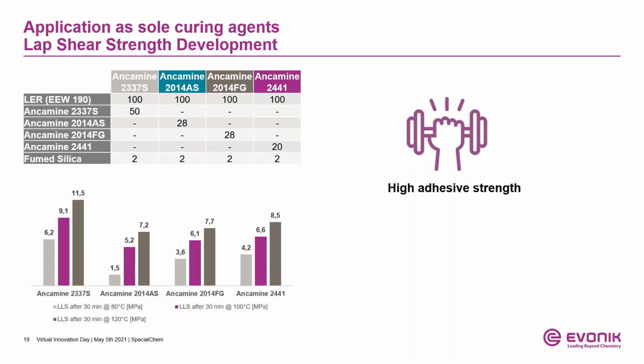Taking the previous results into account, Ancamine 2441 can be seen as the best all-rounder among the modified aliphatic amines, with a good low temperature curing performance, a high thermal stability, the best one out of these products, and also excellent shelf life capabilities. For applications which require lowest possible curing temperatures, Ancamine 2337 should be the first choice, indicated by the results shown here.